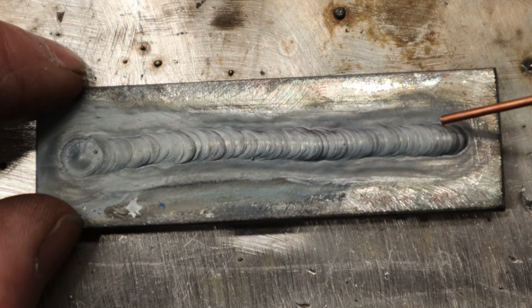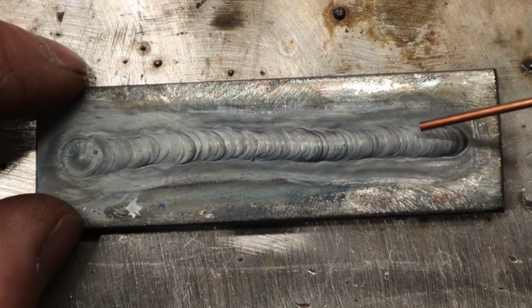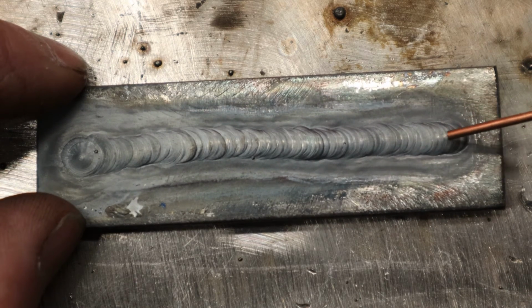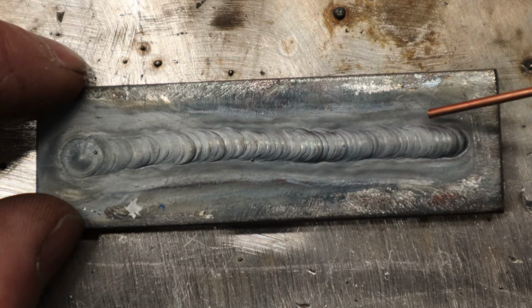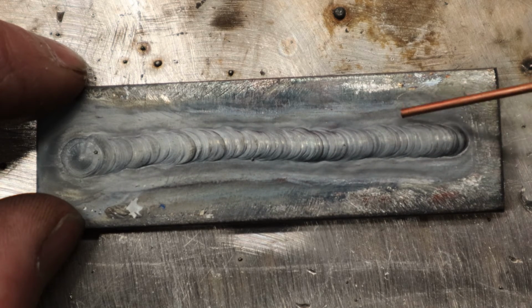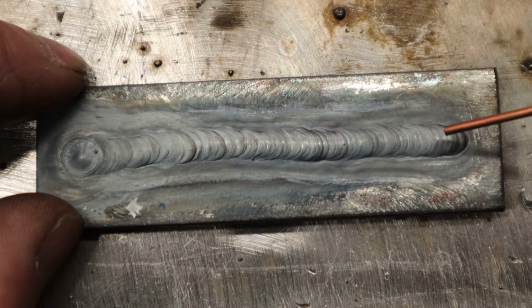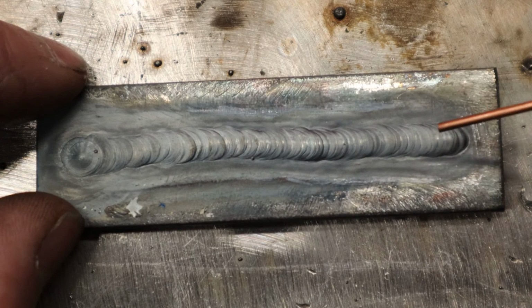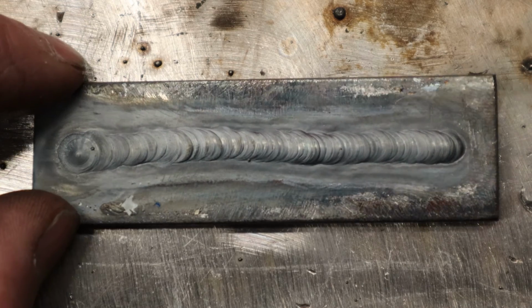The other thing is there is a C pattern here that we can see. That's your individual puddle that is solidifying as you move away. And the distance between those C's is fairly regular. So that means the movement of the torch was steady and the intervals for dipping the filler rod in the puddle were fairly consistent as well.